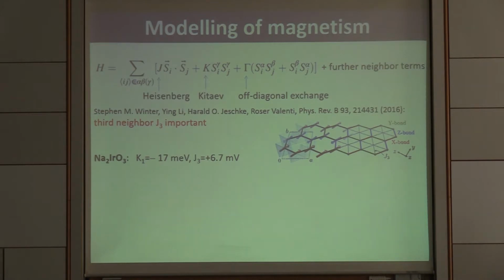For instance, in sodium iridate, the ab initio study by Roser Valentí's group found that the nearest neighbor Kitaev ferromagnetic interaction is really the dominating one, with 17 millielectron volts. And then there is an addition of a Heisenberg J3 interaction, which couples the spins along the opposite side of each honeycomb. As you see here in this zigzag pattern, there is always an antiferromagnetic arrangement between third neighbors, and that's driven by this J3 interaction. For alpha ruthenium trichloride, it's similar, but there is additionally also the very strong off-diagonal exchange between nearest neighbors, and I come to the effect of that interaction in a minute.